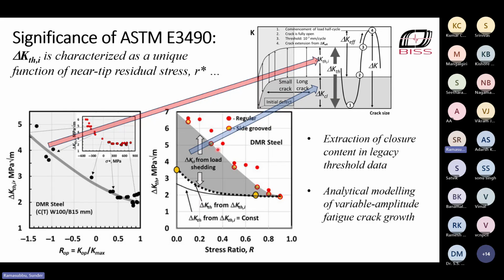And these are actual data points that I've shown over here, which we obtained on a 15 millimeter thick naval low alloy steel, using compact tension specimens, regular specimens, which are the filled circles over here, and the open circles show the readouts we got from compact tension specimens with side grooving. So when you do side grooving, you're imposing plane strain conditions and you're reducing the extent of crack closure. So that's what you get. But actually, the intrinsic threshold is the value that you should get, including the closure component, if it was a closure level that you see in long cracks under non-threshold conditions. So if you take those conditions, this is what you should get.